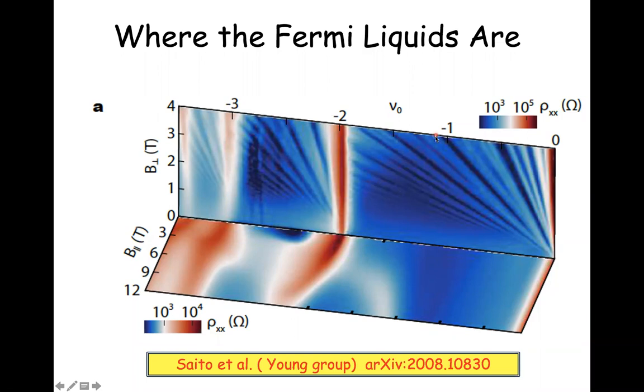And as most of you know, these oscillations up and down of the resistivity reflect Landau levels passing through the Fermi level, and you can read off from these the size of the Fermi surface. And what that tells you is that in this region of density, and the density, of course, is exactly known from the gate capacitance, there are 4 Fermi surfaces, as there should be because of the spin and valley degeneracy. And they're exactly degenerate, and they have a Fermi surface, and nothing special is going on here.